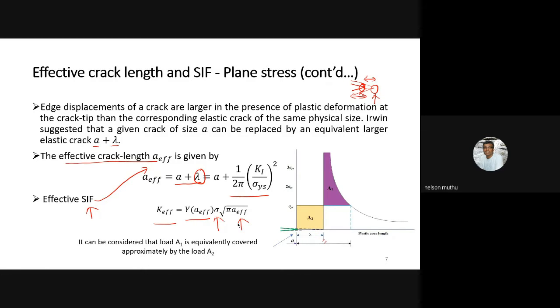You see, so I'll just summarize. The objective is to make use of the LEFM principles in the case of elastic perfectly plastic material. But we were not able to use it because SIF is not defined for inelastic behaving materials. Therefore, we had to make some adjustment. The adjustment was based on some mathematical model. The first mathematical model that we saw was first order estimate, and it was not able to satisfy the equilibrium. Therefore, we went to second order estimate, and we understood that if we have a ligament of length RP, then we can satisfy equilibrium as well as we can bring all the effects of plasticity in that ligament.